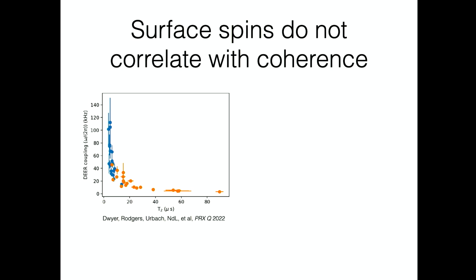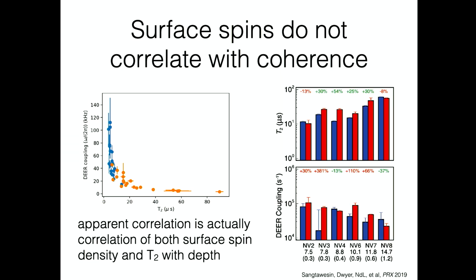However, and I think I sort of gave away the punchline with the title of my slide because I'm lazy about animations, what we discovered is that this apparent correlation for the surface spin is actually a red herring. The apparent correlation is a correlation of both the DEER coupling and the coherence time with depth. And in particular, we could make surface conditions where we could scramble these coherence times and surface spins with respect to one another.